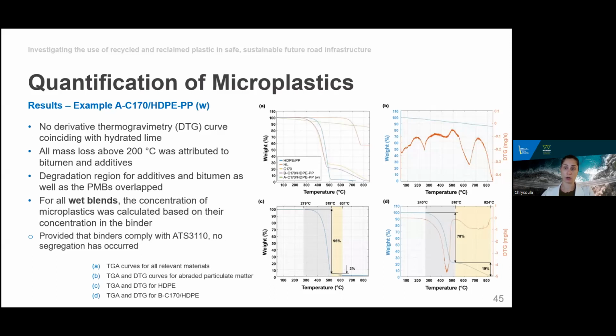Also, we used the Victorian mix, which included hydrated lime. Hydrated lime does not degrade within the examined range. As you can see, it does not degrade within the examined range, and you can see that on the orange curve in figure A. However, we did not find any peaks that coincided with that of hydrated lime.